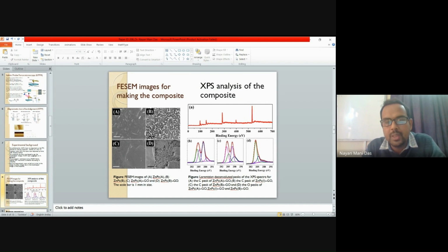Okay, so we did the XPS study in order to see the assimilation between these two layers. If you can see here, there is a peculiar peak at around 285, which shows the interaction of the carbon and the nitrogen, and the other peaks are carbon-oxygen in different valency ranges and the carbon interaction. The carbon-nitrogen peak you can see in figure D is highly increased. From there we can see that the interaction between the graphene and the ZnPc has shown very good promise. The other peaks, like the carbon-oxygen interactions in different valencies and the carbon interactions, have diminished. So from here we can see that the interaction is increased when we use heating for our composite material.